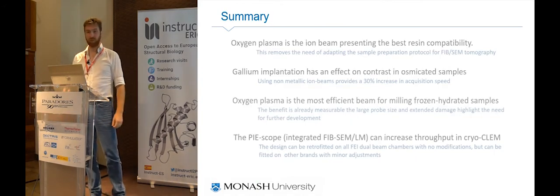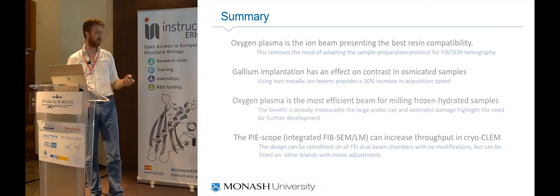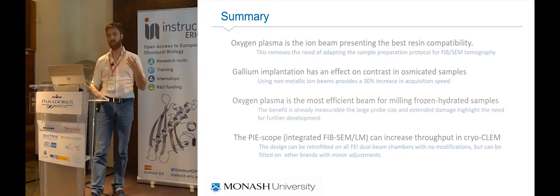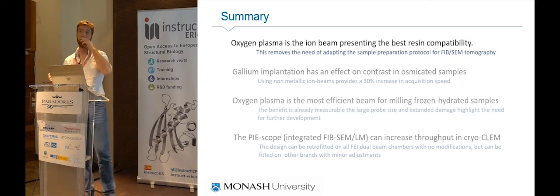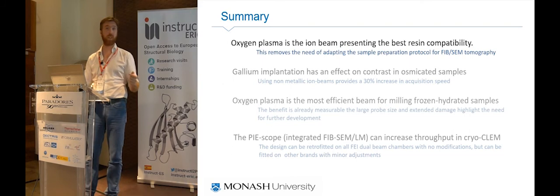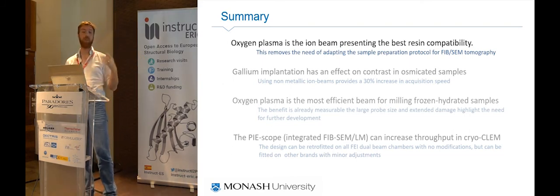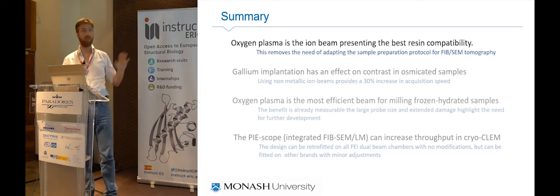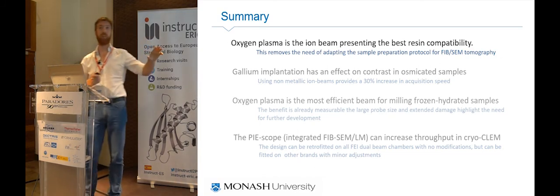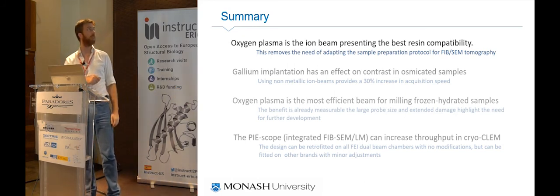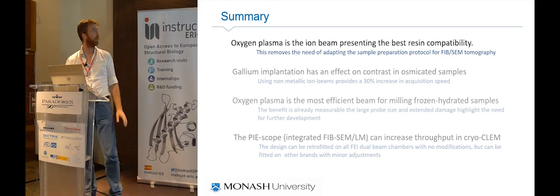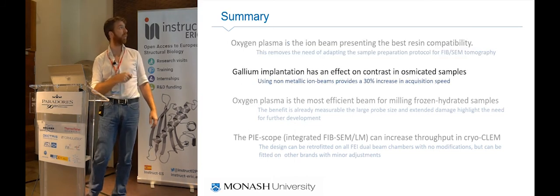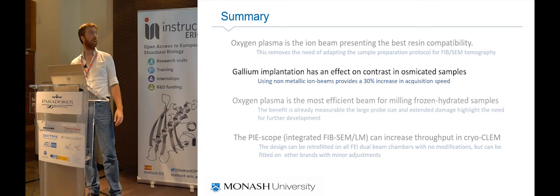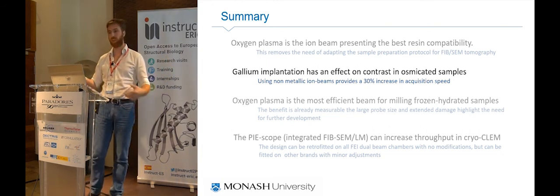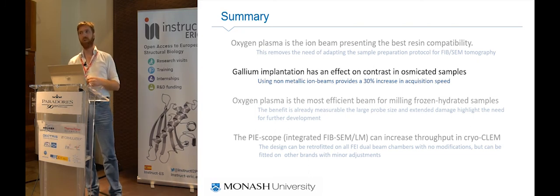So now I would like to conclude because I think the time is running out, and I would like just to summarize. Oxygen plasma seems to be the best, the most compatible beam if you're working on resin embedded samples. So essentially, my take-home message is, if you're doing this and you need 5 nanometers resolution and you're doing very large volumes, go for it. It's fantastic. If you're doing cryo, it's a bit more complicated. Anyway, gallium implantation does have an effect on contrast, and essentially by not using a metallic ion beam, you can decrease your imaging time by 30% roughly.